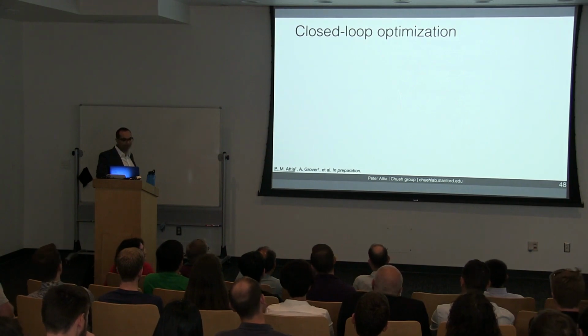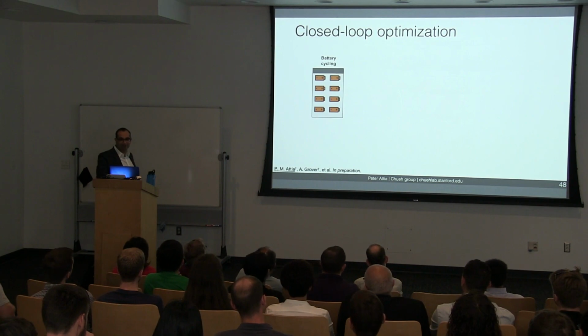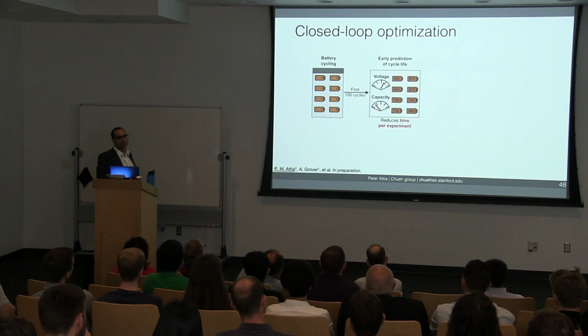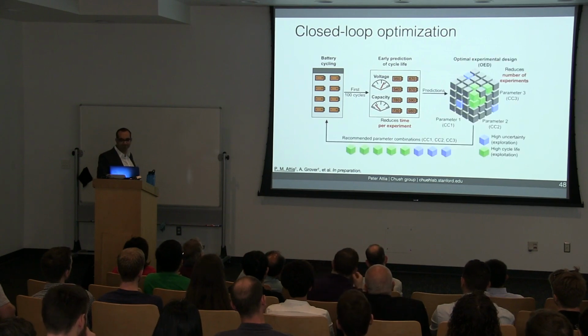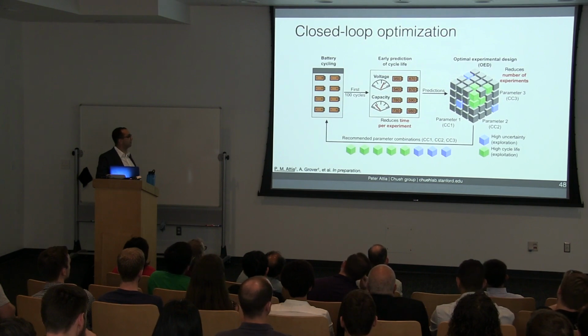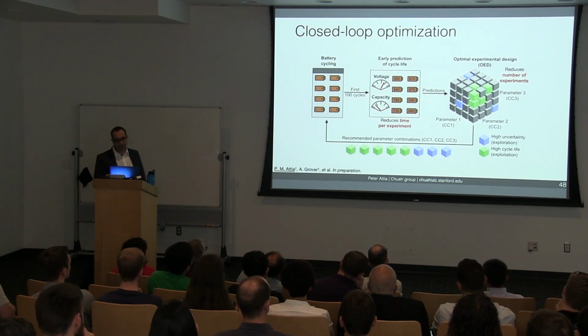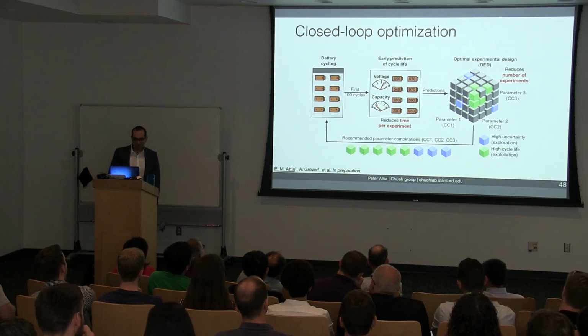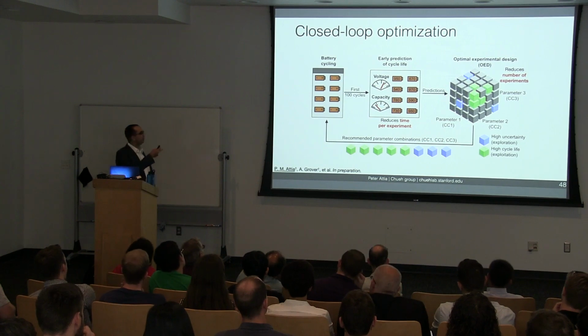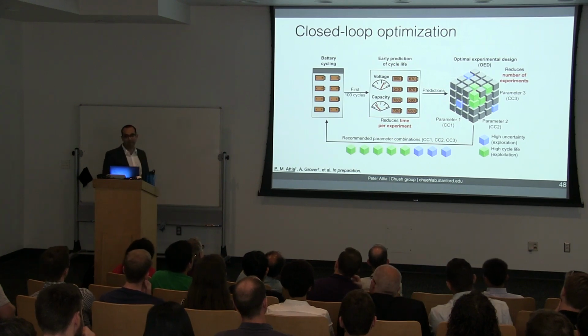So we need a faster way. Our approach is closed-loop optimization. We start with battery cycling. We then feed the initial cycling data to an early prediction algorithm, which reduces the time per experiment. We then feed the predictions into an optimal experimental design algorithm, or OED for short. The role of OED is to reduce the number of experiments, or more precisely, to intelligently recommend the next test to try. The OED algorithm then sends these tests back to the battery cycler, and the process repeats until we solve the problem at hand.